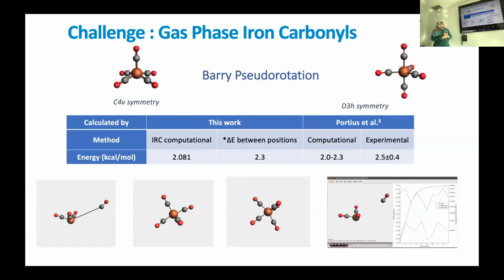So the first thing we did was look at some phenomena of this gas phase carbonyl. This is how this molecule looks in the gas. In the center you have the iron atom, and these are the CO molecules. This molecule undergoes a pseudo rotation in the gas phase, flickering between the C4v symmetry and the D3h symmetry. So we wanted to make sure that the DFT method we use is capable of capturing these gas phase properties.